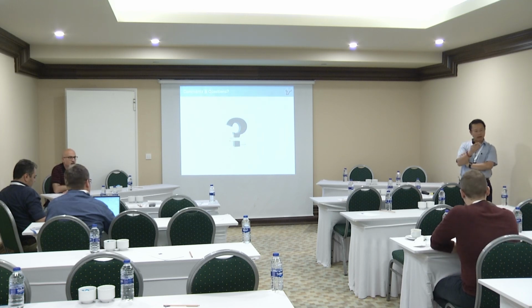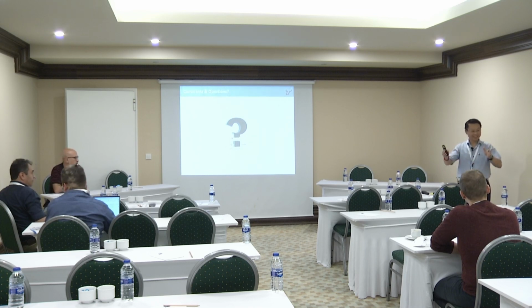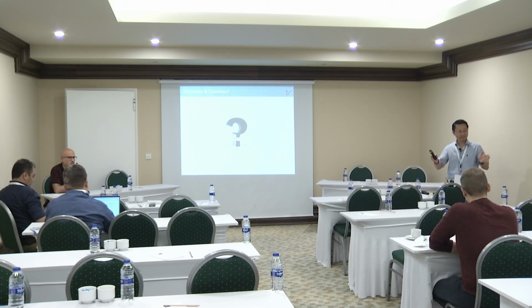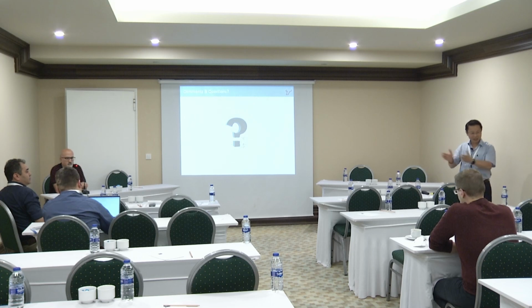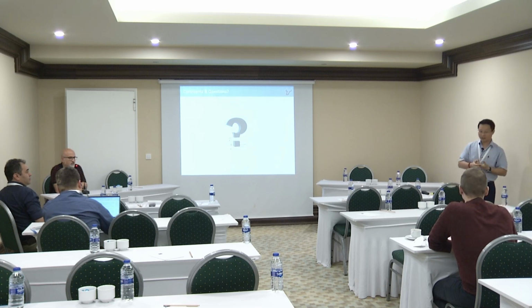In this case, we have to distinguish between two effects. Exchange bias here is more related to the magnetic interface. It's not between the magnetic and the non-magnetic interface, but it's kind of in between. For example, pure TMD would not have magnetic properties, but because of defects, it has polarized spin at the defect sites, and eventually it becomes a kind of defective magnetic material. Therefore, when I showed you VSe2 and MoS2, it also induced exchange bias, plus it's like a magnetic proximity effect. That's why when you cool down the materials in a magnetic field, it's not only shifted, but also aligns some spin which is misaligned from the MoS2, and that turned out to be very interesting.